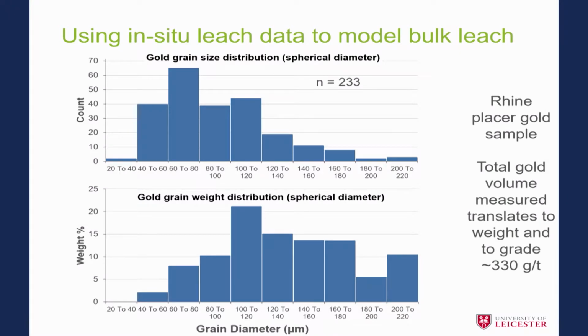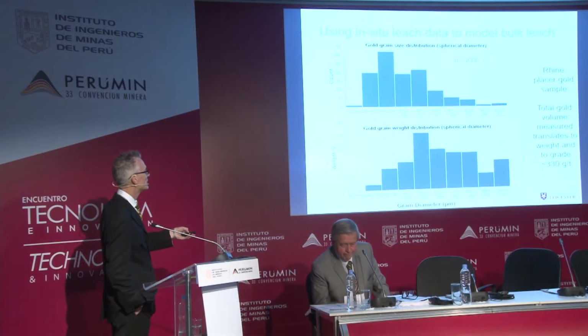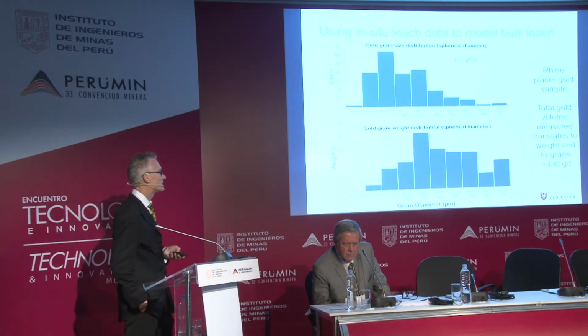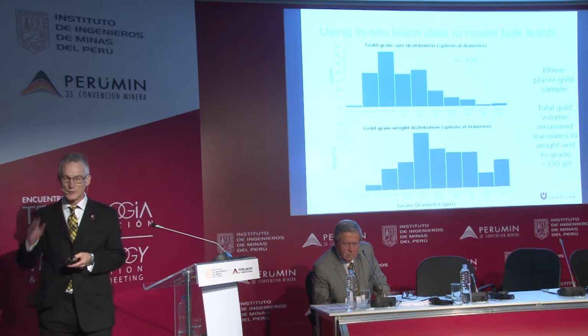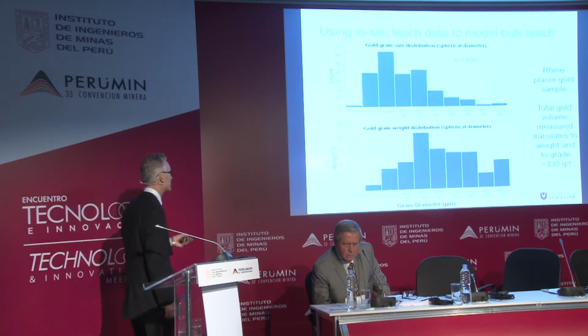Okay, so we gain data not on a few grains, but 233 grains. We can look at the grain size distribution. It's pretty coarse stuff here, dominantly 70 microns, but up to 200 microns. We can take that grain size and convert it to a weight, and we can see that our dominant weight size class is 100 microns. But interestingly, the big grains, there's only 3 of them here, but they contribute about 10% of the gold. It's always important to look after your nuggets.